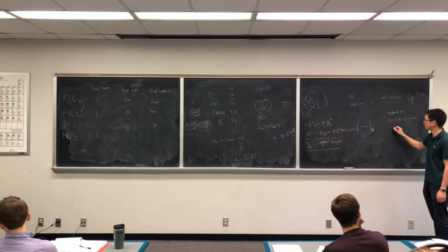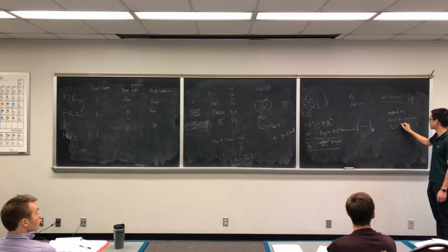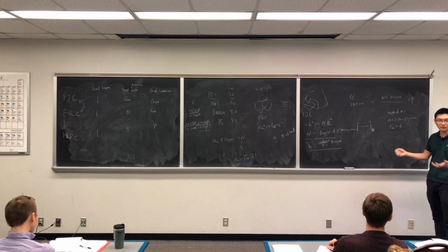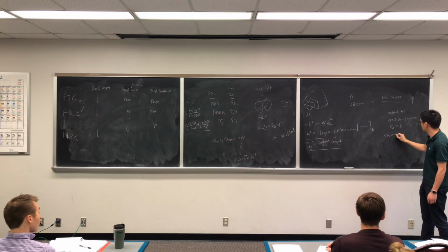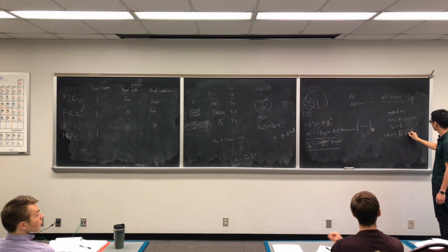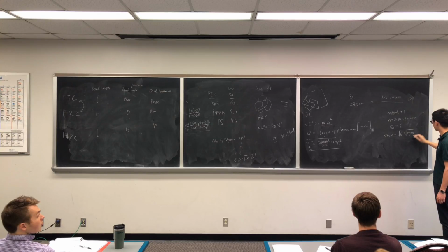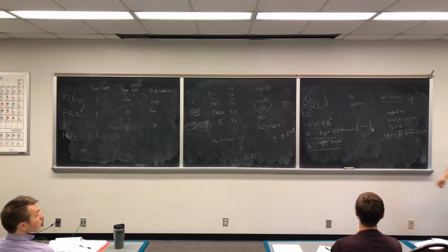But let's say this is somewhere around 6. Okay? So you can calculate the end-to-end distance. H will be equal to the root of 6 multiplied by n, then multiplied by a bond length, 1.5 angstrom, and you can calculate how big the end-to-end distance is. This is one way you can get it.